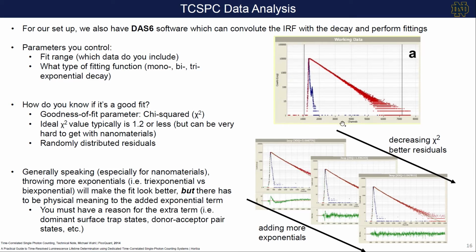I think it's really important to mention that the data out here, which is being binned in the later channels or later time points, corresponds to literally tens of photons, compared to 10,000 photons being counted over here. So the majority of your decay is happening within this first decade, or first decade and a half, or 2 decades. This is representative of the majority of the sample. Way down here, if you're counting 10 photons compared to 10,000, this is essentially noise.